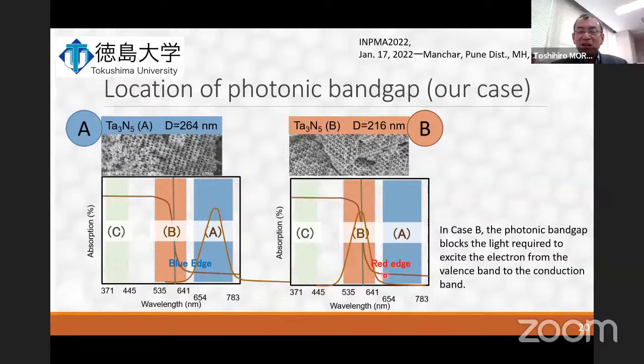In sample B, the photonic band gap reflects more photons in the red color region, a part of which is shorter than the absorption edge in wavelength. Namely, many photons with high energy cannot be absorbed by tantalum nitride because the photonic band gap right here is almost within the absorption edge. Okay, in case B.